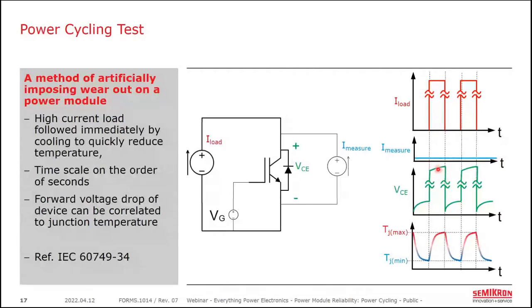And even more important than the magnitude of the current is deciding how long you wait before you take the measurement, because there's other things going on here, like carrier effects in the semiconductor itself that you have to worry about, that the charge carriers have to evacuate before you've taken your measurement, but you can't wait so long that the chip has started to cool. So I would say it's arrived at experimentally, but it's typically on the order of milliseconds.